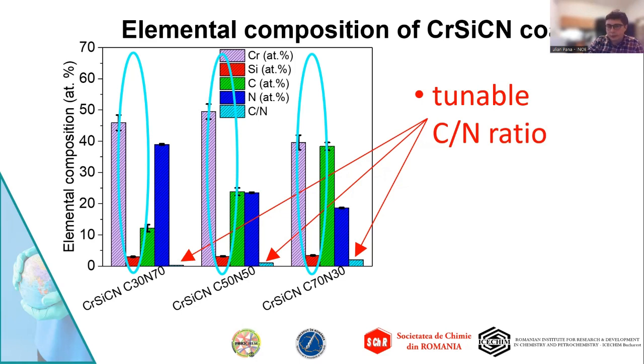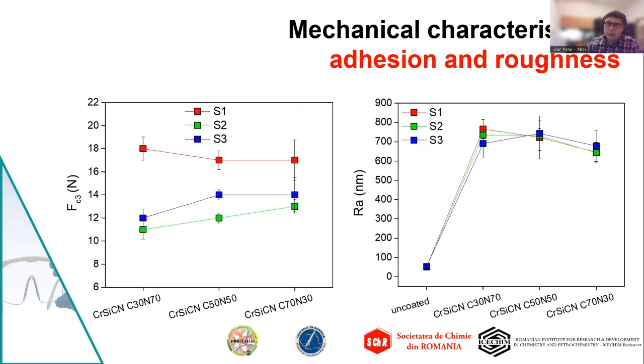This is a result of the chromium silicon cathode that we have used during the cathodic arc evaporation process. The adhesion was evaluated via scratch test. The aim was to pinpoint the critical force where the delamination of the layer occurs. We have observed that the coating deposited on steel 1 exhibited good adhesion, I would say outstanding adhesion, with critical force values ranging between 17 and 18 newtons.